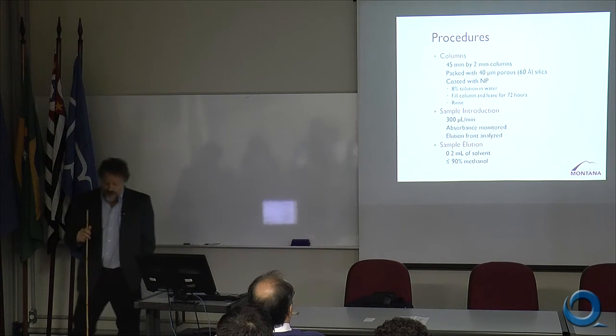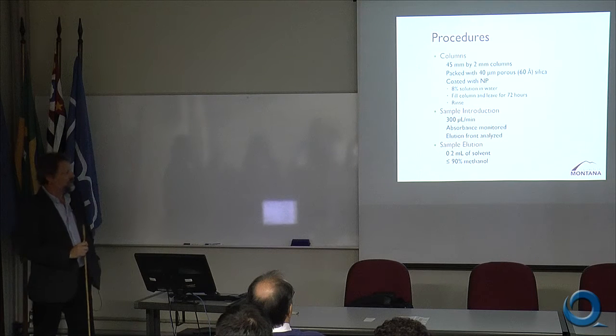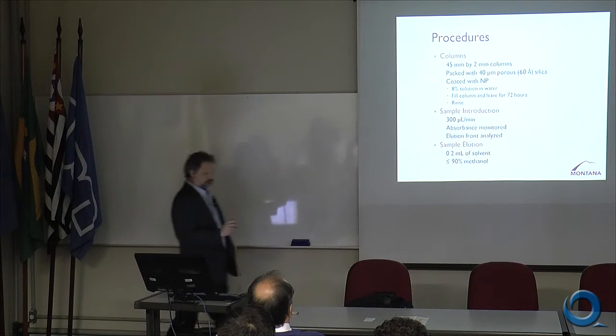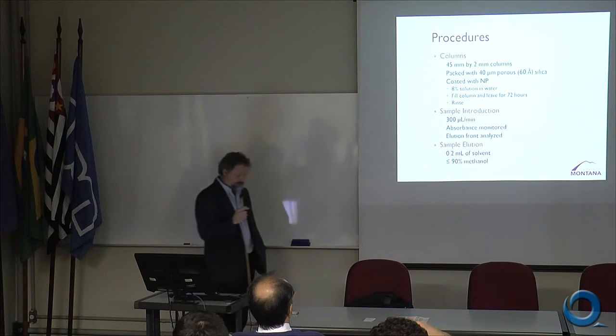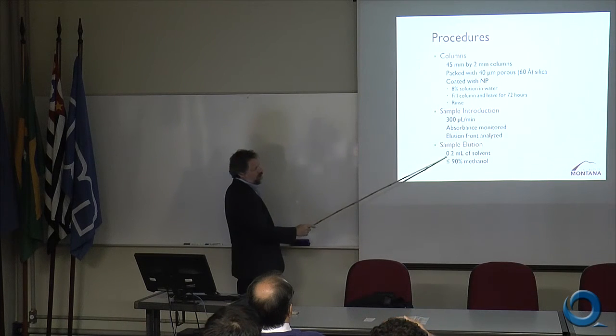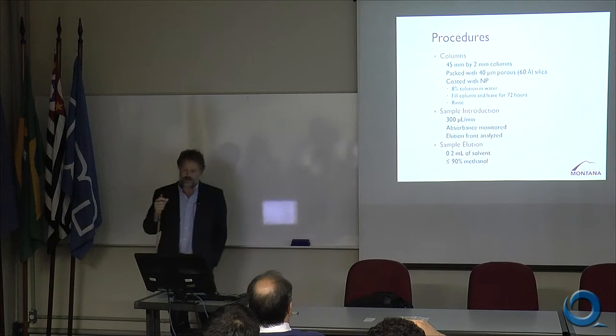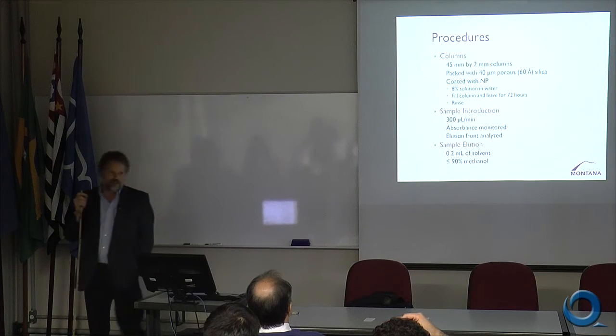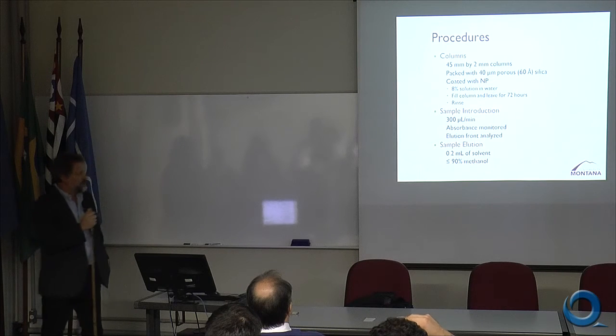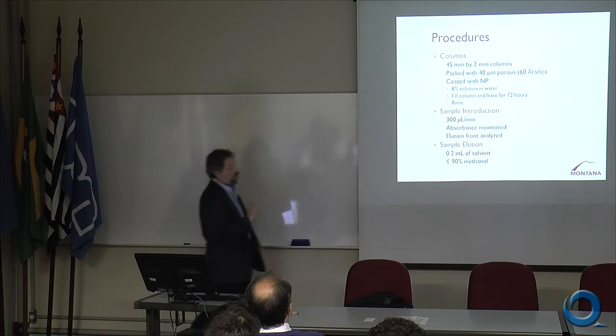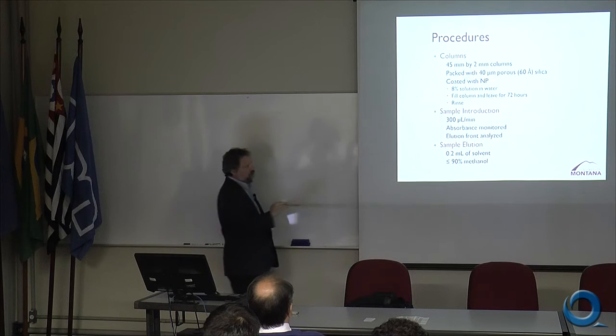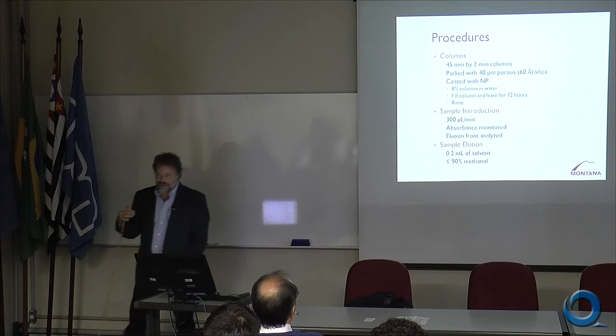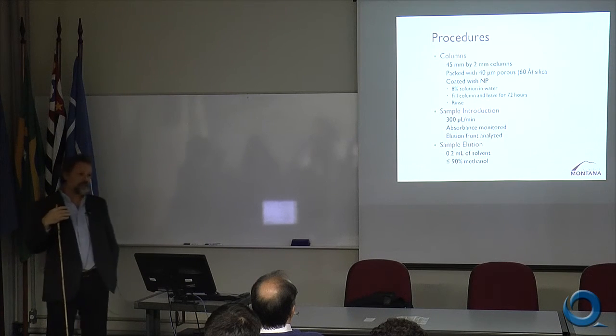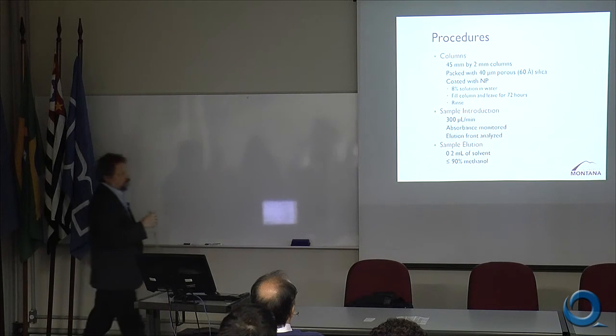We started out trying to use 100% acetonitrile or 100% methanol, and we lost about a month of work, probably a couple weeks of work, because every time we would inject 100% solvent into this system, it would degas, and we would get air bubbles in the detector, and it would take about an hour to get the detector to settle down and start to work again. So we eventually realized that if we just went to 90% methanol, it was still effective at washing the column, but we didn't get the air bubbles in the system, and we could do a lot more experiments.